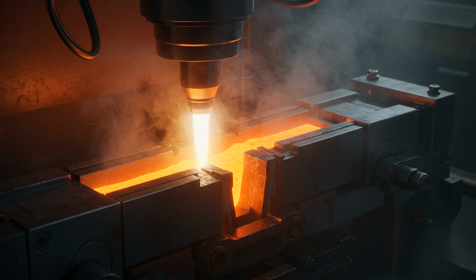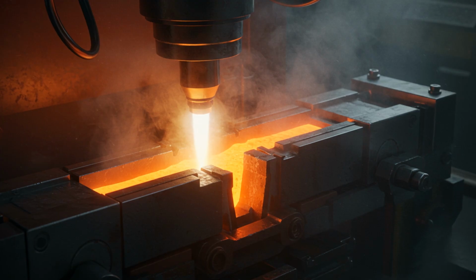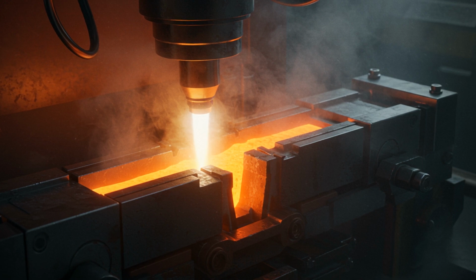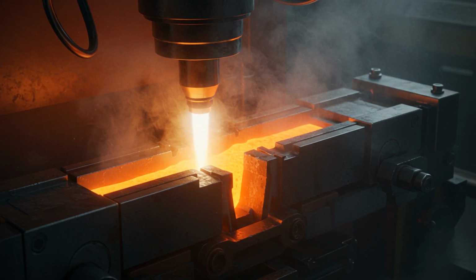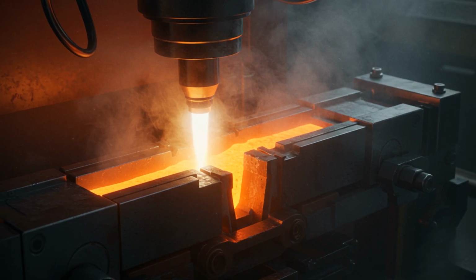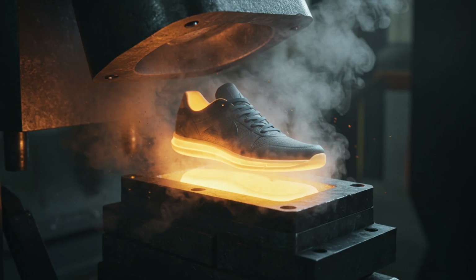Then, with a sudden burst of hydraulic power, the molten plastic is injected into the mold cavity at high velocity. This takes only a few seconds. Inside the dark, pressurized heart of the mold, the EVA fills every nook and cranny, but it's under such immense pressure that the gas produced by the blowing agent is dissolved into the liquid plastic, much like carbon dioxide is dissolved into a bottle of soda. The material is currently a dense, hot mass held captive by the steel walls. To the naked eye, nothing is happening, but on a molecular level, a massive amount of potential energy is being stored, waiting for the pressure to drop. This is the most cinematic moment in footwear manufacturing, the pop.